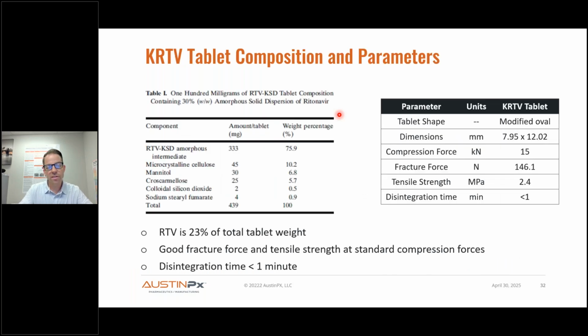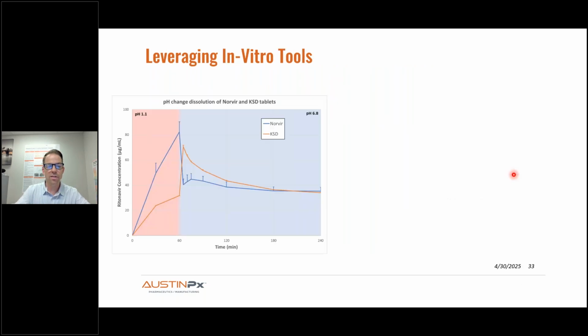And now let's talk about tableting. So that's another key component, as I said before. You can optimize drug load, but you also should optimize the ASD load in the final tablet. So our KinetiSol material is directly compressible, has excellent compression properties, which I'll get into in a moment. And we were able to increase the weight percentage of the ASD in the final tablet to about 76%. So we were able to get 30% drug load, 100 milligram tablet, and about half the size of a Norvir tablet. And you can see with good tensile strength, excellent disintegration.